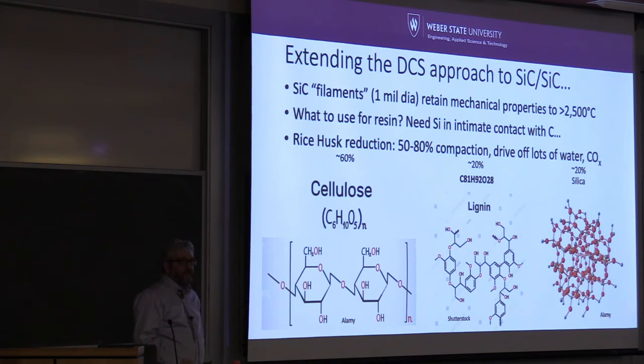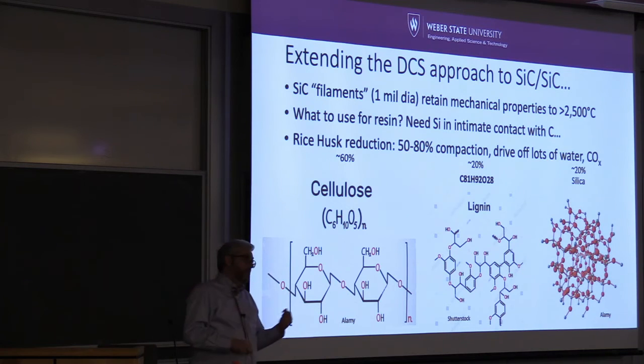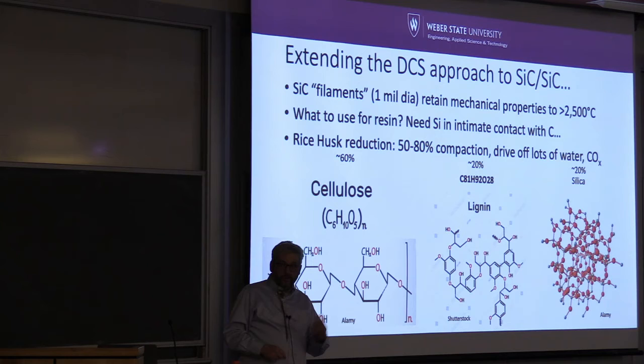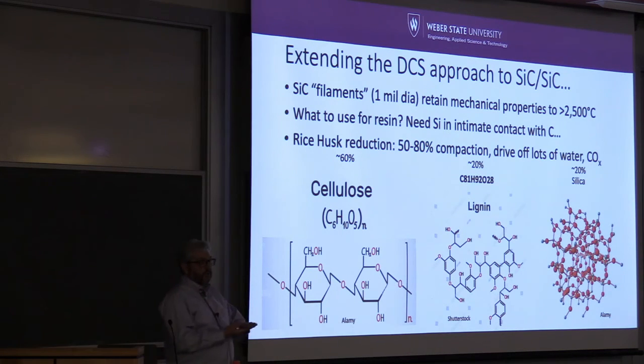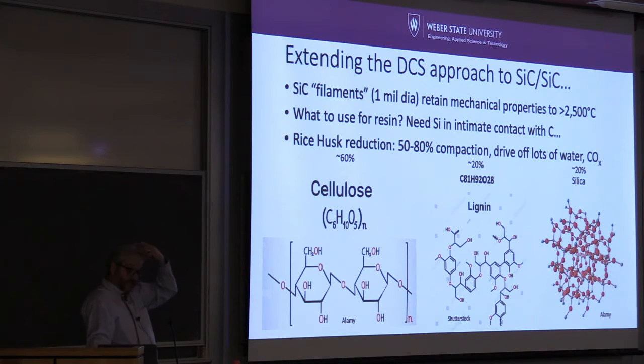What about the cellulose? Is that going to be conductive or non-conductive? Iffy? Kind of iffy? Probably not very conductive compared to lignin, which has a lot of these aromatic structures, which when you overlay them, it's the aromatic structures that give you the conductivity in organic materials, right? So potentially rice husks could be used as a matrix material. Let's say you put carbon fibers in them, or boron fibers in them, or silicon carbide fibers in them, and then press this, and then you can get, in theory, you can produce some nice fiber in silicon carbide matrix material. Okay, so that was the flight of fancy, and I was on my way to the grocery store to get some rice husks.